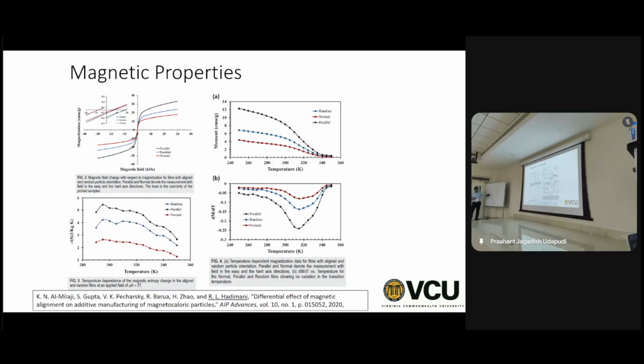Okay? So if you have a polycrystalline, what will happen? This is a single crystal sample, right? The a-axis is the hard axis, the b-axis is the easy axis for magnetization. You don't call it easy and hard for other property measurements, for example thermal conductivity or Young's modulus or electrical conductivity.